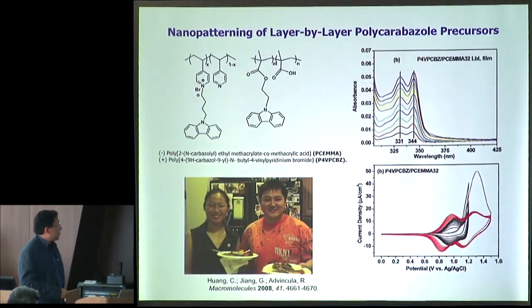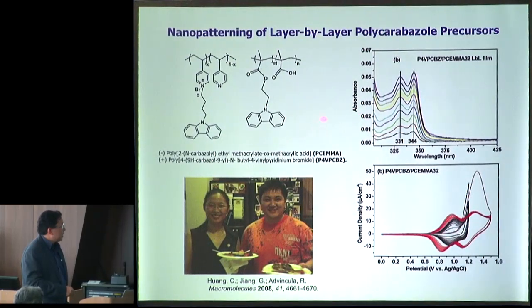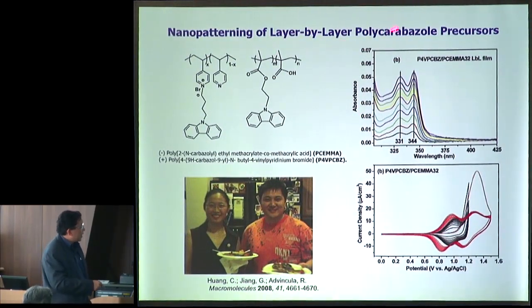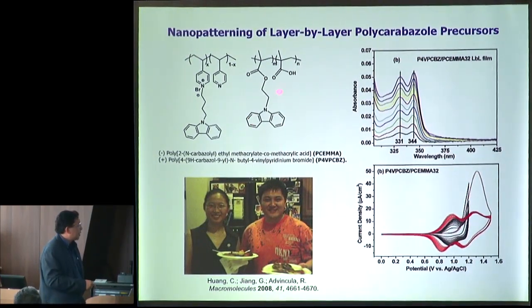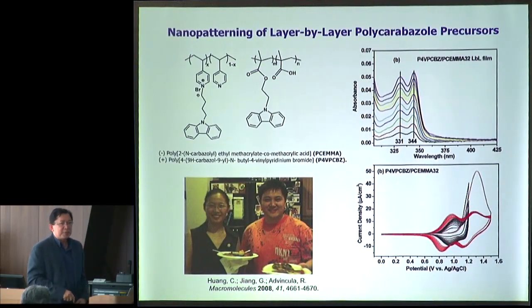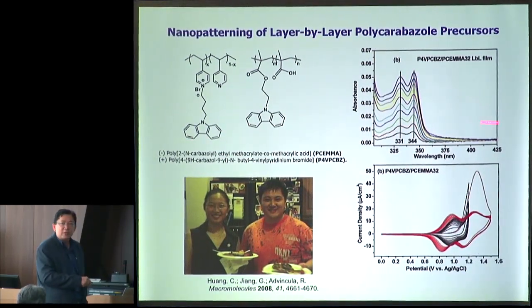Okay? So we got many papers, and in fact, one of the easier papers to work on was on a layer-by-layer polycarbazole precursor. So if you know layer by layer, of course, all you need is a negatively charged polyelectrolyte and a positively charged polyelectrolyte. You pair them up layer by layer in a beaker experiment, and in this case, these are polymers where we actually have carbazole units that like to react and cross-link. Okay, so we built that film and we increased the number of layers and we cross-linked them using electrochemistry, and